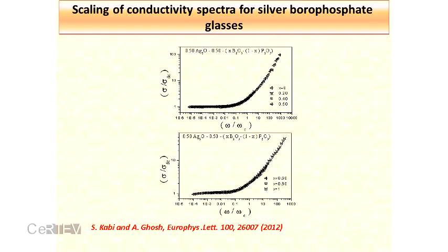If the composition range is like this, 0 to 0.5, then there is perfect superposition. So in this composition domain, there is one type of mechanism. Here also, in the 0.6 to 1.0 range, for the same glass systems but with a different composition range, you can see the perfect superposition. So this is according to our model, which predicts that if there is no structural change in a particular composition range, then there will be perfect scaling. And if the structure changes, there will be a change in the scaling parameters.